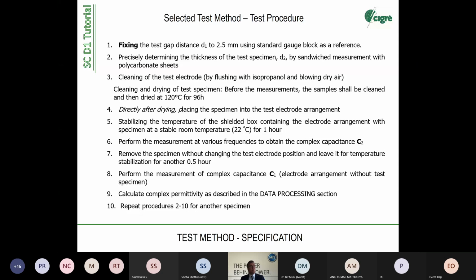Temperature, if you look into Arrhenius equations, and Arrhenius is coming along with dielectric phenomena, because you have energized states in dielectrics, all depending on temperature. The temperature has a very large influence on the dielectric phenomena. So we have to control the temperature, perform the measurements at various frequencies to obtain the complex capacitance. Do all the things that are written here.